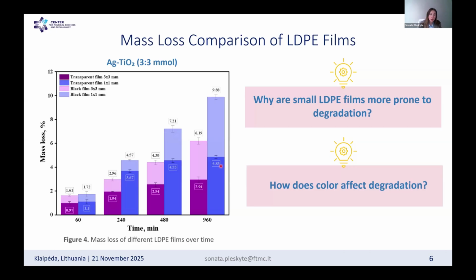And when we are talking about the black films, here manufacturers most often use carbon black, especially for plastics which we are using for outdoor activities. And why we got the higher degradation efficiency for black colored LDPE films compared to transparent films could be related to the heat absorption effect, since black films absorb more light, and the temperature of the black colored LDPE films of course increases. And so far we know that temperature is one of the key factors in photocatalytic degradation. So the higher the temperature in our reaction system, in most scenarios, the better the photocatalytic degradation performance we have.